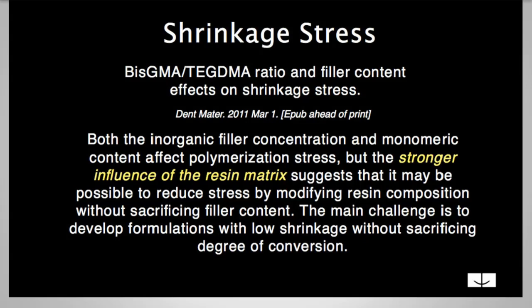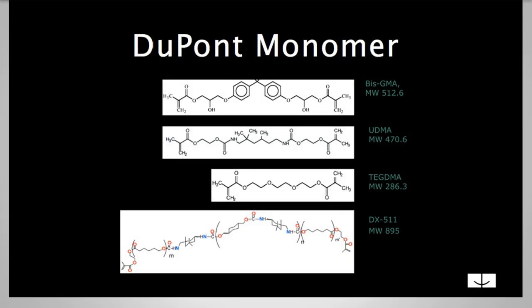So what GC did with Color is that they created a whole new monomer in the resin matrix. They found something that was a lot heavier. So they went outside of dentistry to DuPont and they said to these chemists, hey, we want you to create this new monomer. Now, I actually met some of the chemists who did it. Oh my goodness, I could barely understand what they were saying because it was so far above my head. But when they broke it down into these terms, essentially it's a very, very heavy molecular weight monomer. As you can see here on the right, bis-GMA, TEGDMA, all those different things. Here's their molecular weight, and then you can see what the molecular weight is of this new monomer in the resin matrix of Color.